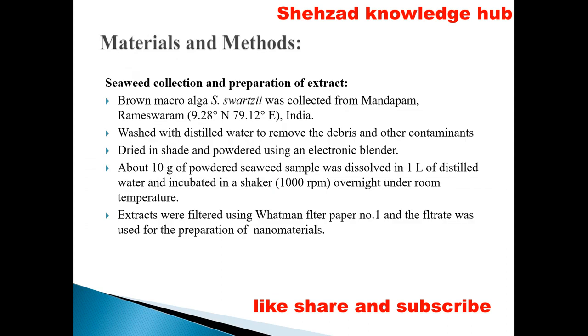Materials and methods: seaweed collection and preparation of extract. Brown macroalga S. swartzii was collected from Mandapam, Rameswaram, India, washed with distilled water to remove the debris and other contaminants, dried in shade, and powdered using an electronic blender. About 10 grams of powdered seaweed sample was dissolved in 1 liter of distilled water and incubated in a shaker overnight at room temperature. Extracts were filtered using Whatman filter paper number 1, and the filtrate was used for the preparation of nanomaterials.